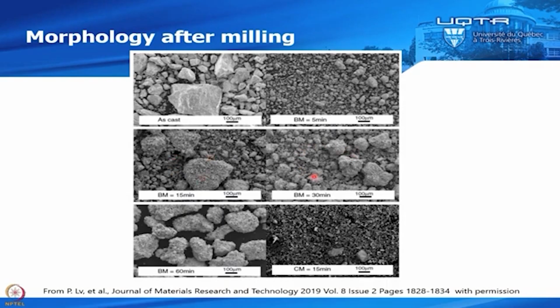And this agglomeration will continue for 30 minutes and even 60 minutes. And now you see that all these particles are agglomerations of the small particles that you see here. So you don't see any small particle anymore because you have agglomeration of all of that. And for cryo mill, you see that the particles are very small, but we think it's because it was milled in air and you have a lot of formation of oxide, and it prevents agglomeration and it makes decrepitation of the particle.